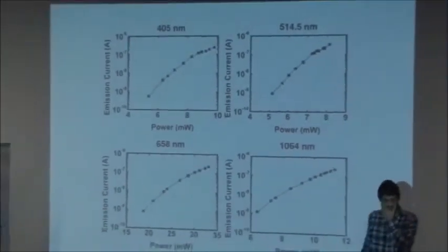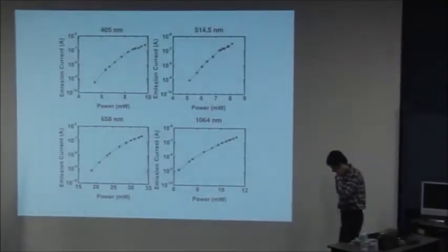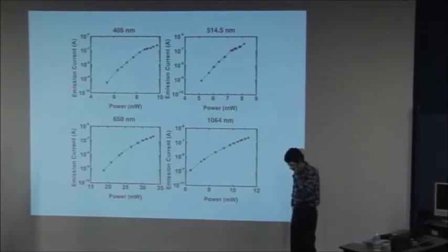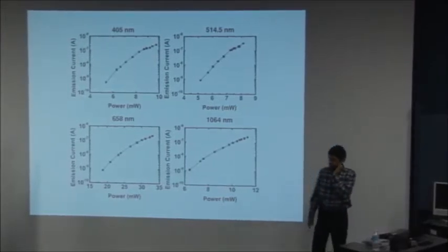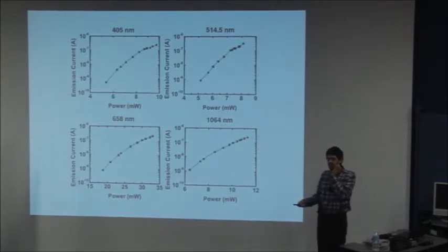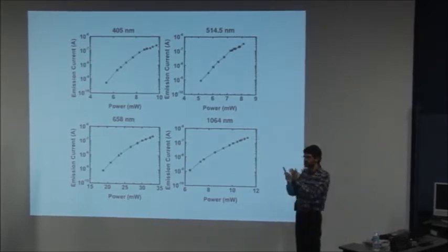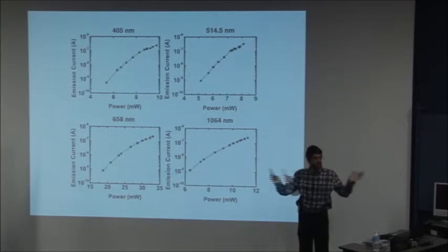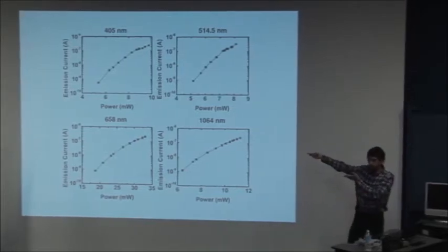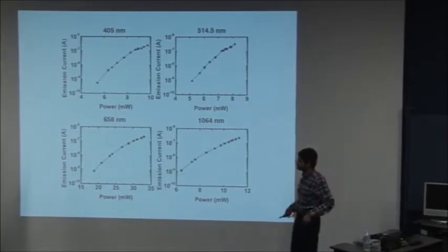I told you that we started doing this with a green light, and it was how we got into this accidentally. But very soon we realized that it's not really that strongly dependent on wavelength, because nanotubes are a good absorber of light in a very broad band. They're very black. And so, like I showed in the previous movie, in that case it was an infrared light.